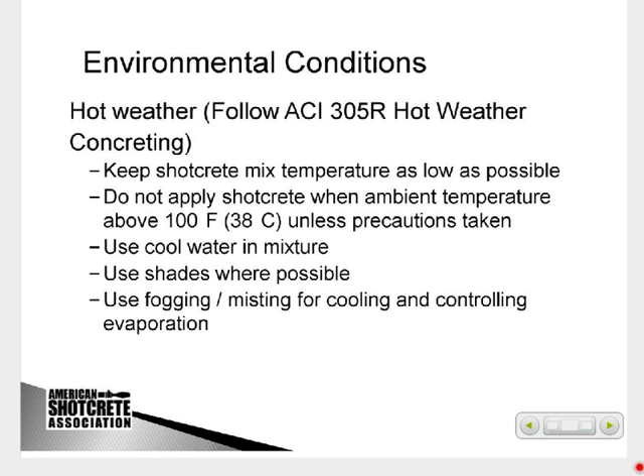Also in shotcrete, it's not unusual to put up sunshades to keep the area that's being shot shaded, so you're not building up the solar radiation gain of heat. And also then to fog or mist the surface to help cool it and to control that early age plastic shrinkage cracking by keeping the surface from evaporating quickly.